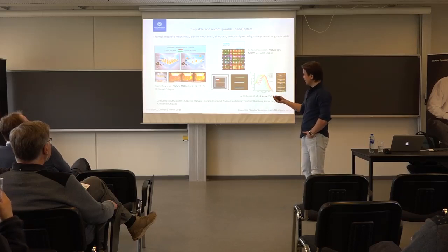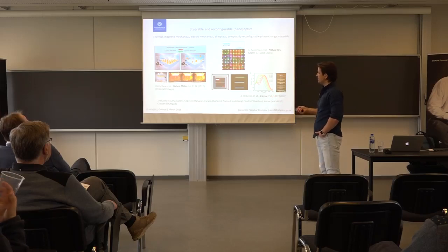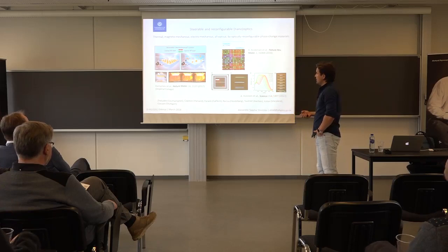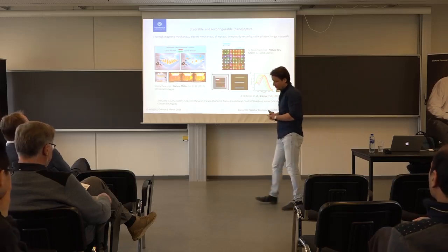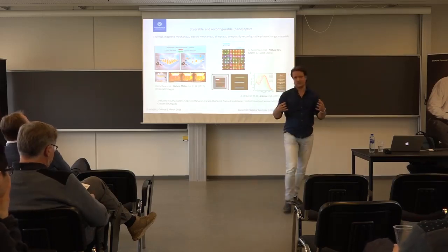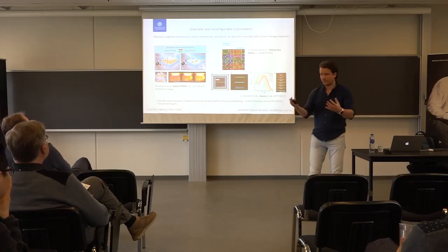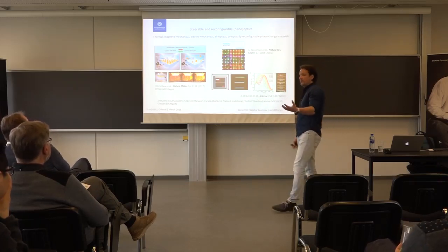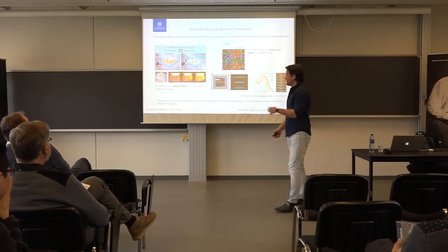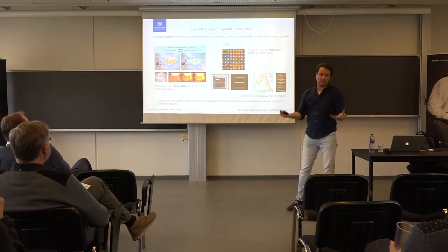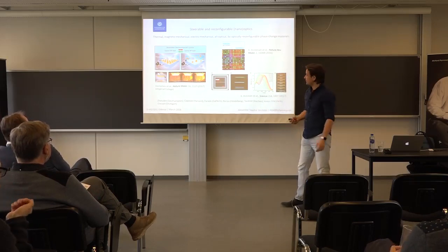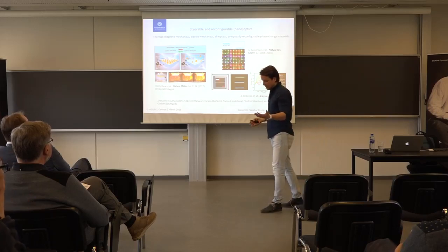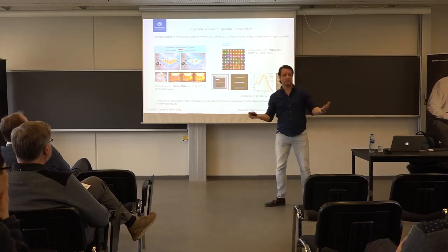So just for you visually how it works, you have a surface, let's say, with nanoparticles made of gold, and of course these nanoparticles support the so-called localized surface plasmons. So the plasmons are just collective oscillations of electrons in these particles. There are a lot of free electrons in these particles. Thus they oscillate, and they are able to couple to light. And actually this is one of the reasons why stained glass windows work, for example.